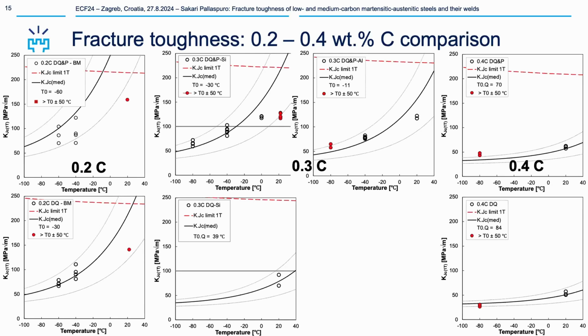For instance, if we use this fracture toughness reference temperature T0, we see that it's well below 0, even in the minus 50, minus 60 degree range for low carbon steels. But if we jump to 0.4 carbon, it's not there. They are not tough at all.